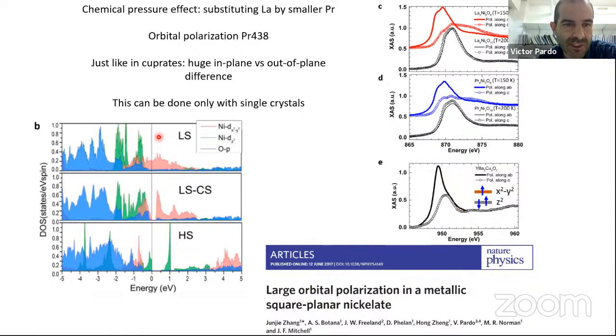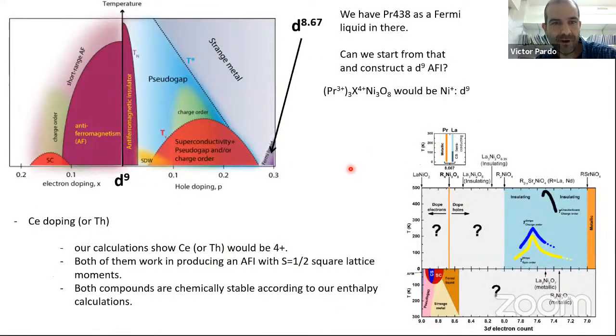The reason for this, we see it here in the low spin density of states of our calculations, is that you have at the Fermi level and above, basically the in-plane orbital, which is this x squared minus y squared. It has a much higher occupation than the z squared, which is the out-of-plane orbital, and that's why you get this much higher orbital polarization for the in-plane orbitals. And this resembles the physics of the cuprates. So we are in a very good position.